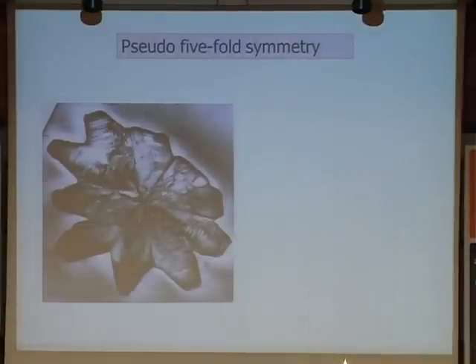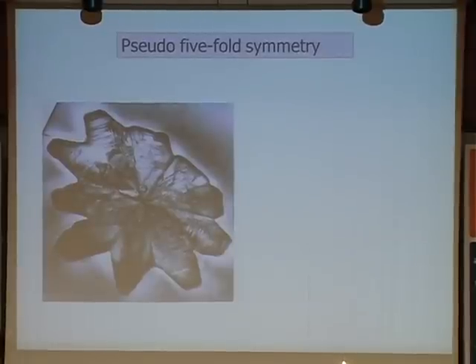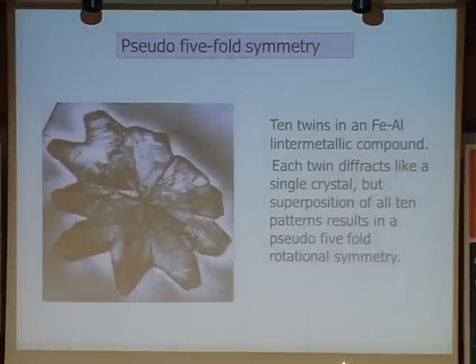However, there is a pseudo 5-fold rotational symmetry, as I told you, with twins. And here is an example. This is a micrograph that I took many years before the discovery, somewhere in the 70s. And it was so trivial that I never published it. Later on, I discovered that one Chinese crystallographer published about 5 papers on this picture. There was nothing to it, but some people can do that. Okay, so what we have here is a crystal which is found in the aluminum iron system, and you don't have to do anything special. Just cast an aluminum iron composition, and it appears in many compositions. And large crystals like this grow. You can see them in an optical microscope. They are large. So here is one in the transmission electron microscope, which is quite nice.